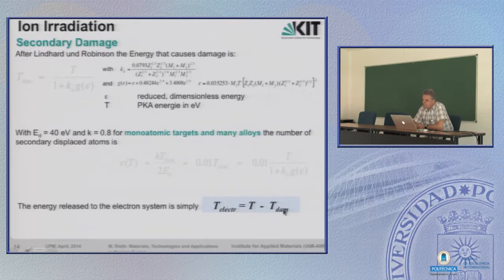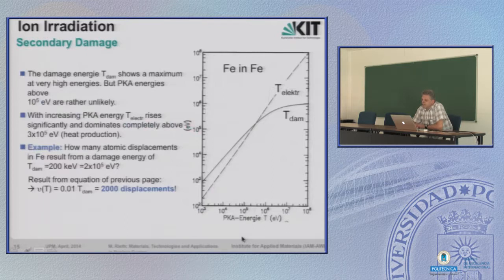This leaves only one question. If we have T_dam, what happens with the rest? That's the produced heat, what we called energy for electron excitation. And in iron, for example, depending on the primary knock-on atom energy, you see that in general we have to deal with energies for damage which are lower than 100 keV. More than 100 keV are rather unlikely, while the produced heat doesn't saturate, it simply goes up with rising energy.